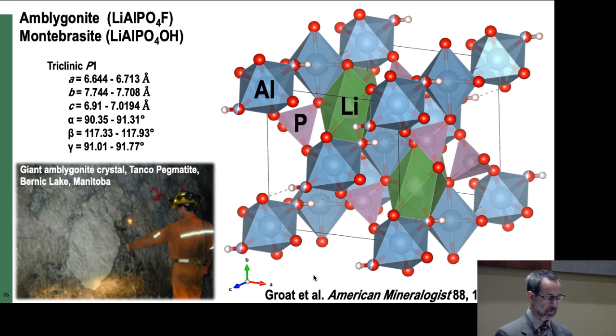Let's look at another mineralogical example where fluorine substitutes for hydroxyl in this lithium aluminum phosphate, amblygonite and montebrasite. And what happens is it causes a positional disorder of the lithium site. So, you know, this is the crystal structure. Again, it occurs as large crystals in granitic pegmatites covering the whole solid solution range.